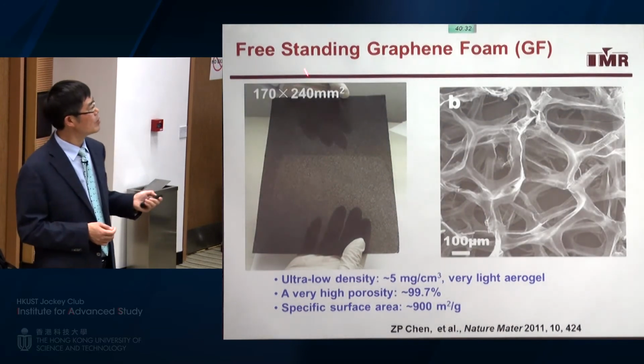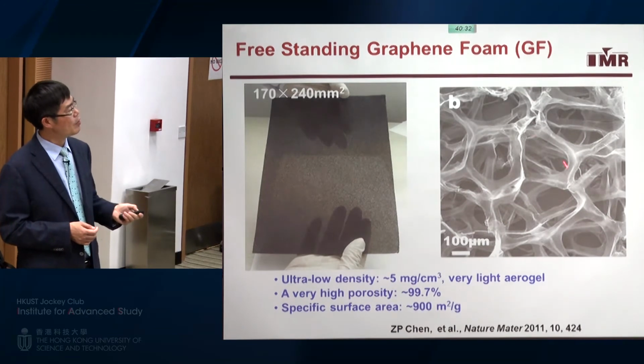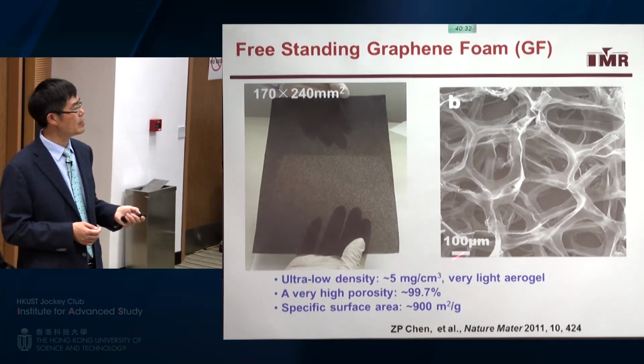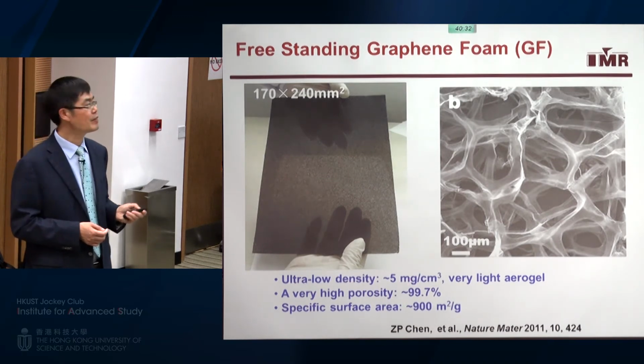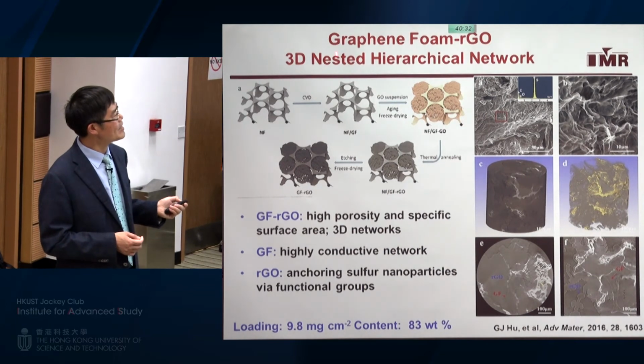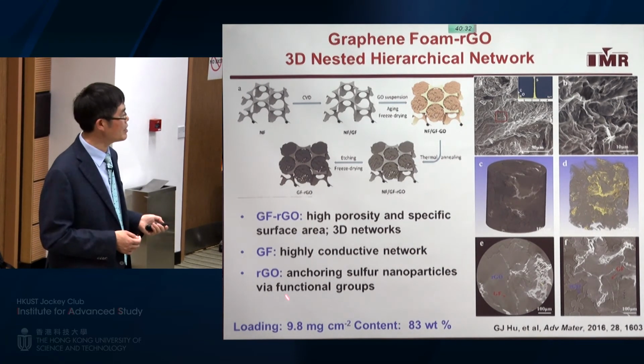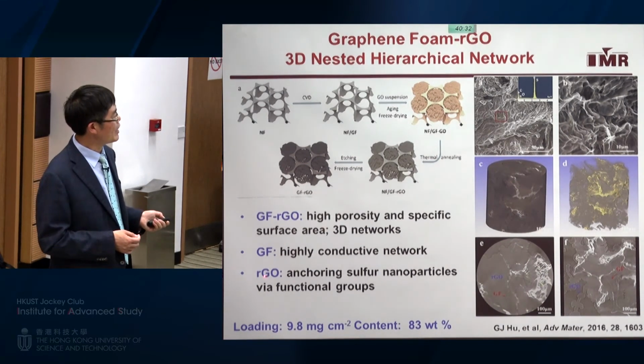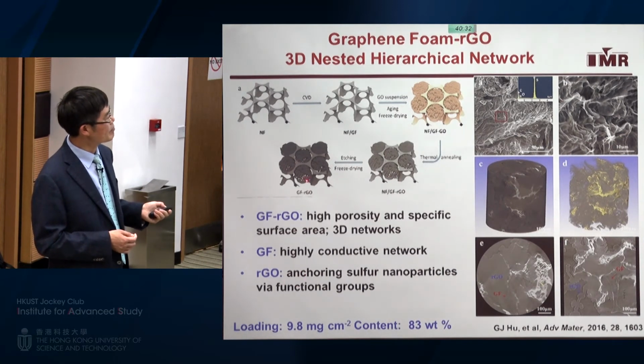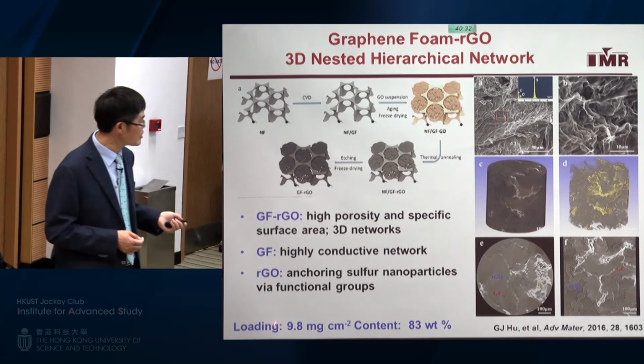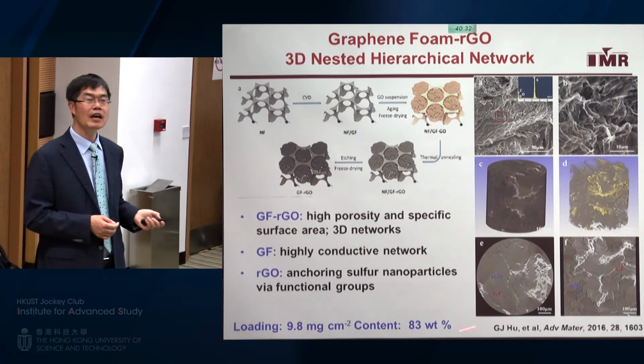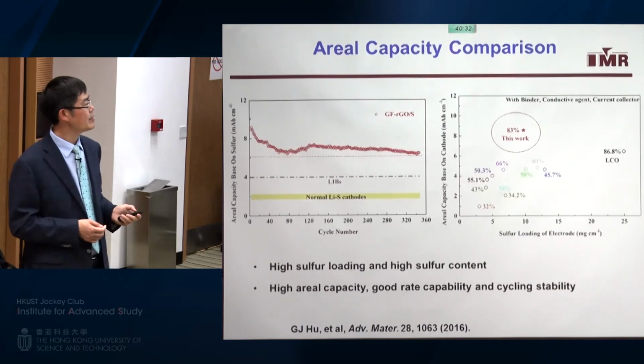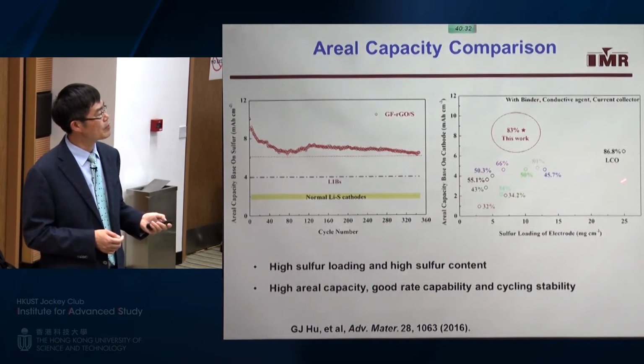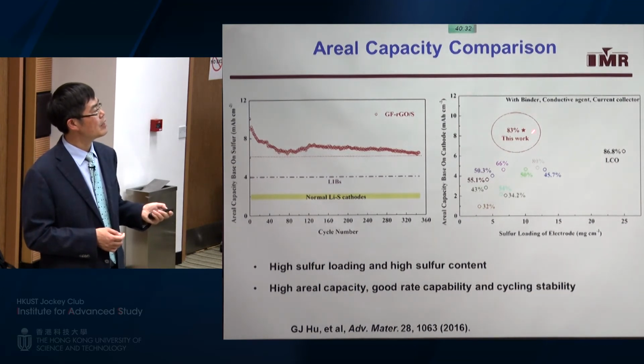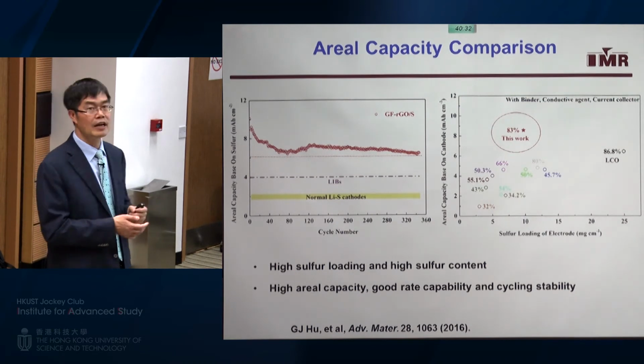So some years ago, we made this freestanding graphene foam with a three-dimensional interconnected porous structure, very light, high porosity. So then we try to make a nested hierarchical structure by incorporating the sulfur on reduced graphene oxide, then put those hybrid materials into this graphene foam. In this way, we can have a very high loading and also very high sulfur content. So then we can have very good performance compared to the previously reported results. Our results are very outstanding.